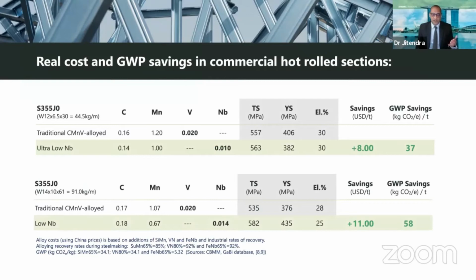So to give some industrial examples, these are two 355 sections I've given, where one was typically alloyed with carbon, manganese, vanadium, and one was then done with ultra-low niobium. And these are commercial examples, and you can see here that in the current market conditions, we can save $8 a ton using an ultra-low niobium addition, or $11 a ton for that particular manufacturer. And there were also subsequent savings in global warming potential because we're overall using a lower content of raw materials from the alloying perspective.